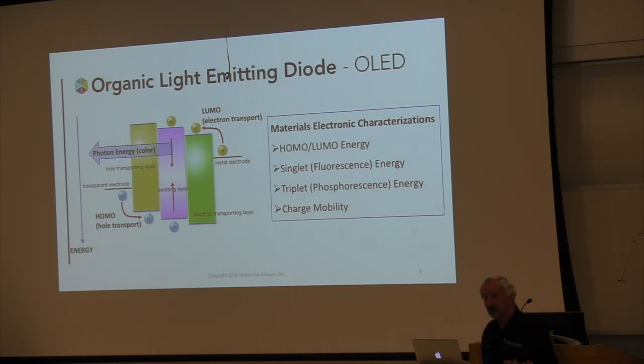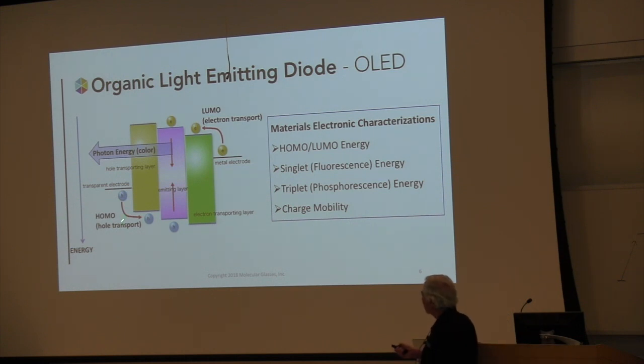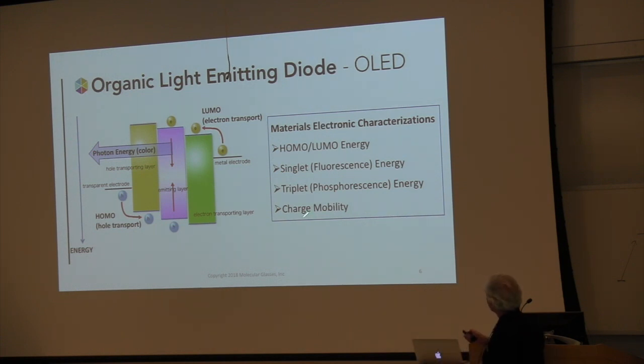So what are the organic material characteristics that are of interest? What you want to know in a molecular sense is the highest occupied molecular orbital, HOMO, where positive charge will be injected. So you want to know what energy that is with respect to vacuum. The same way, electrons are injected into the lowest unoccupied molecular orbital, LUMO, and you want to know what that is with respect to the vacuum. You also want to know what the photon energy is, and what the excited state energies are of the other materials, so you don't quench the photon energy that you want to have emitted. So these are the things you want to know: HOMO-LUMO energy, fluorescence energy, triplet energy. You also want to know the mobility of charges through these materials.